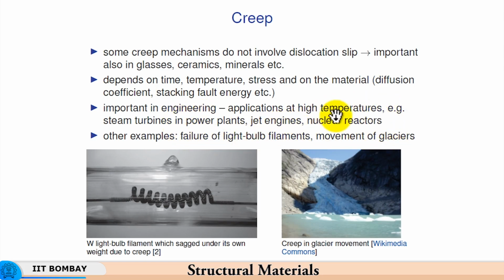In nuclear reactors, you have an additional problem of radiation damage taking place. Radiation damage results in generation of vacancies, which encourages diffusion of atoms. So, there are many other factors which come into play in the case of nuclear reactors. Creep is aggravated or accelerated by virtue of radiation damage, because in the presence of vacancies, in the presence of defects generated by radiation damage, you have creep rate going up quite significantly.